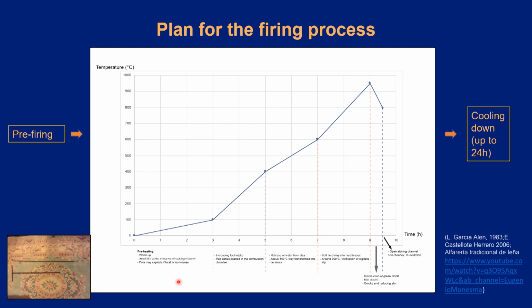From ambient temperature to 100 centigrades, we warm up and dry the kiln dome. A small fire will be set at the entrance of the stoking channel to gently heat the kiln. If the heat is too intense, trapped steam may make the pots explode. We must always accept that some pots are going to be lost at this stage.